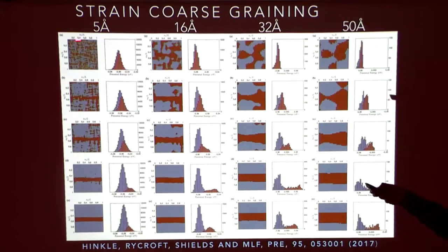You can see for small coarse grainings, the two histograms separate, right? They both look pretty Gaussian. They separate, but they're still heavily overlapping even at the highest strain when we're really heavily localized. For a much coarser coarse graining, they're indistinguishable. Then when we localize, you see the two distributions are quite distinct.